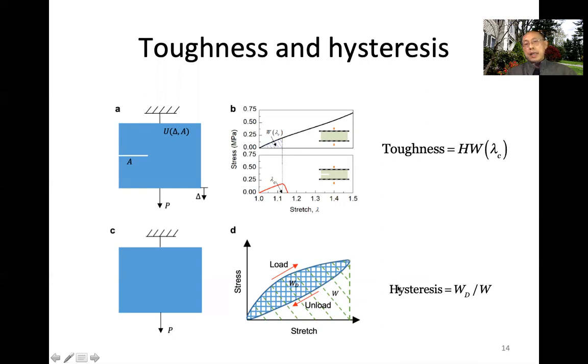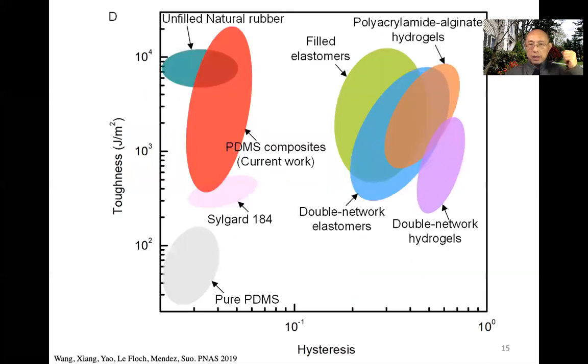So for most applications, you want to have a very small hysteresis, right? During loading and unloading, no energy dissipation. However, when a crack is extending, you need to have enormous energy dissipation. So that's the ideal material you want. Now this composite really achieves this behavior. So here we plot the toughness and hysteresis. We want a material to have a high toughness and a low hysteresis.